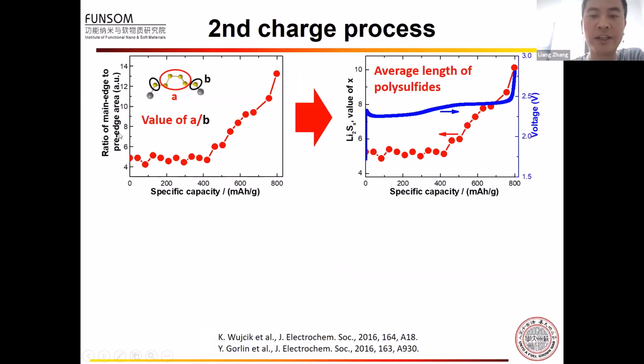Because there's a linear relationship between the area ratio and the average length of the polysulfide, we can directly convert the area ratio to the average length of the polysulfide. The right figure shows the average length of the polysulfide at different states of charge. At the beginning of the second charge process, the average length of the polysulfide is around 5, which means the average lithium polysulfide is like Li2S5. This clearly indicates the presence of lithium polysulfide at the beginning of the second charge process.